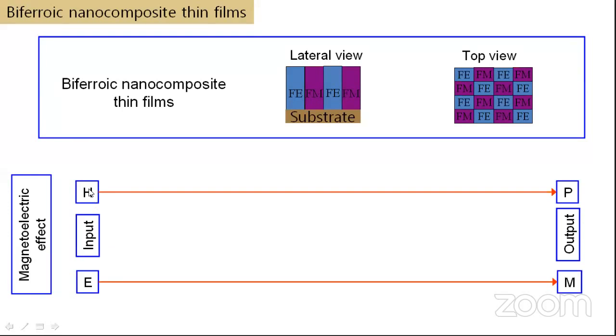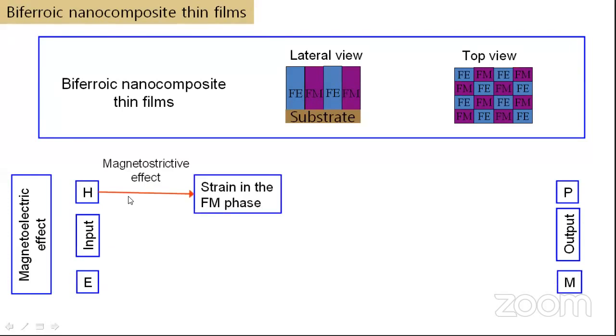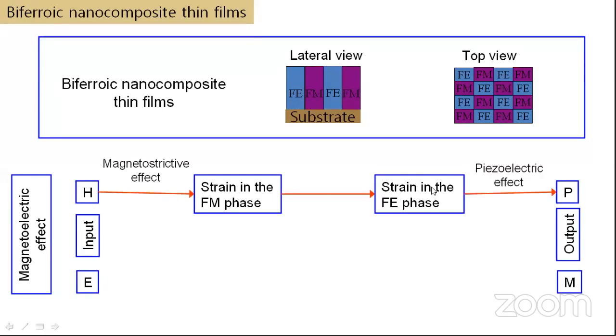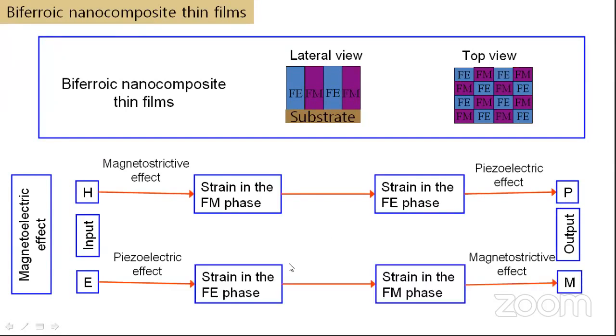If you give an input of a magnetic field, due to the magnetostrictive effect in the ferromagnetic material, there is going to be strain in the ferromagnetic phase. This ferromagnetic phase is coupled with the ferroelectric material, so that is going to produce a strain in the ferroelectric material. The ferroelectric is also a piezoelectric material, and because it is piezoelectric, the electric polarization can switch. So by applying a magnetic field, you can switch your electric polarization. Similarly, by applying an electric field, you can switch your magnetic polarization, the inverse effect.